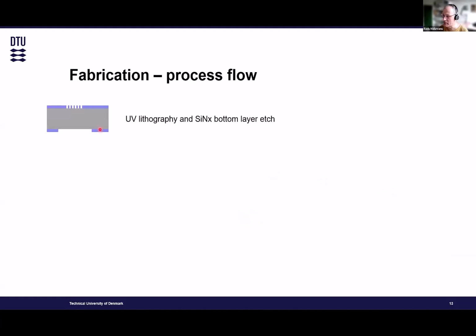So after we do this, when we start to KOH etch, although we start here, we also start slowly to etch up here at the membrane, and that actually explains all our problems, because if the pattern is in a rectangular shape, then we have a rectangular membrane. It's also bigger than it's supposed to be, because there is the underedge here that makes it bigger. So we end up with a structure something like this, that is very similar to what we saw in our experiments.